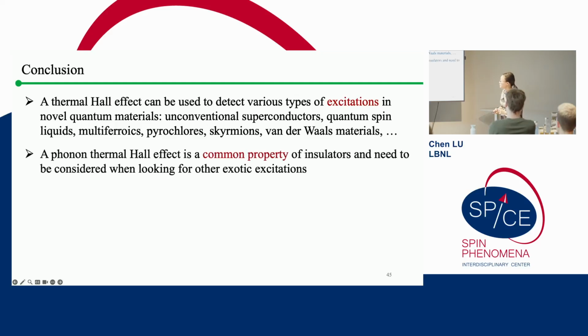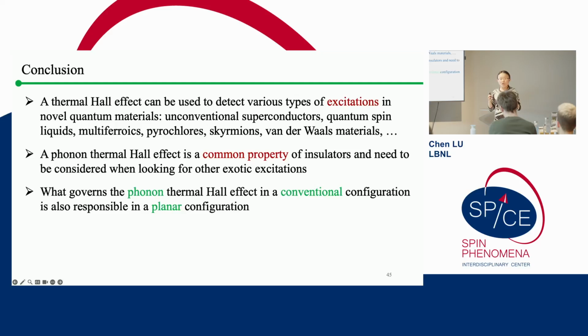Okay. The next take-home message is that my focus in this talk is the so-called phonon thermal Hall effect. At the very beginning, people believed it was something very rare, but very recently we started to realize it's probably a much more common property of insulators than people believed before. However, there still remains an open question: what is the mechanism behind the phonon thermal Hall effect? There have been various theories that try to explain it, but they were usually only applied to one type of material. They cannot be a universal theory to actually explain it. So now the question is whether there exists a universal theory to explain the phonon thermal Hall effect.